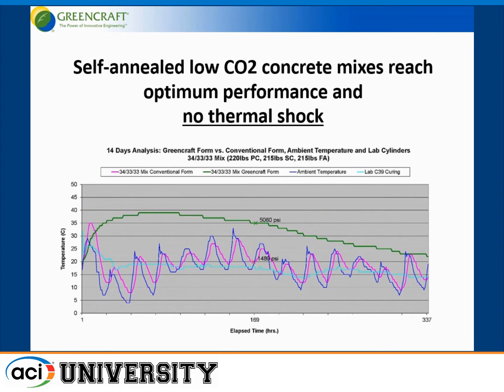Now, we mentioned that we can take high supplementary cementitious material concrete mixes and use those. This is a mix of 220 pounds of Portland cement, 215 pounds of slag cement, and 215 pounds of fly ash type F. And this is a mix that you wouldn't even consider for anything other than, you know, a mass concrete foundation or pour. And we put it through the same curing environment.